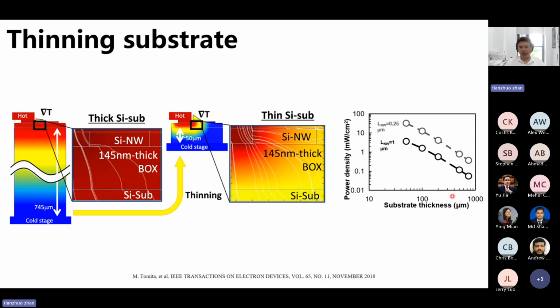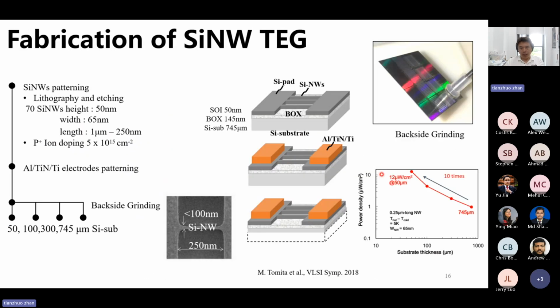So by thinning silicon substrate from 745 micrometer to 50 micrometers. And we also fabricate the silicon nanowires using the CMOS process technology, and so we use the backside grinding technology to thin the silicon substrate, and so the experiment results also show that the power density has been improved by more than 10 times by thinning the silicon substrate.